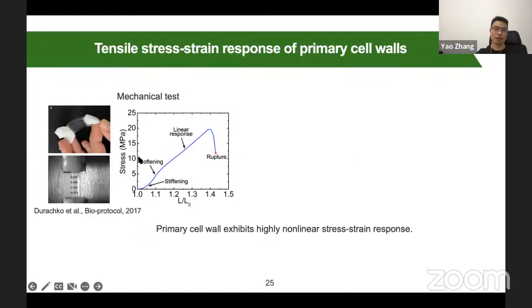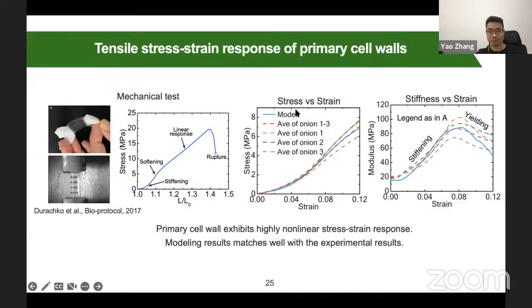So this is our experimental result. From the macro scale, we can get a stress-strain curve, and we want to use the modeling to reproduce this stress-strain curve. This figure shows the experimental result. Actually, we use three onions, and this blue line is the model. If you look at the strain, we just calculate the strain range from zero to a strain of 0.12. In this region, you can see that the model result matches the experiment result.